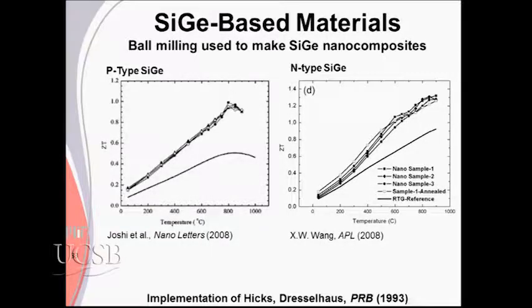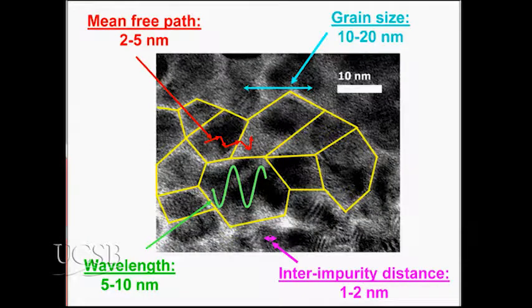So this shows that, yes, nano works for both N and P type. This is silicon germanium. You can use any other material. But this is something that's a good idea to do. And so the physics behind all of this is you want to have within your grains, you have the grain boundaries, and then you have some defects like point scattering centers. So you put an impurity, either going substitutionally or interstitially, something like that. It will scatter, hopefully, phonons more than electrons. So you have to figure out how to do this. And people here have many ideas that go far beyond our ideas. But you can see that we have some kind of ordering in the material. You could see some local structures. And that's a good thing to have.